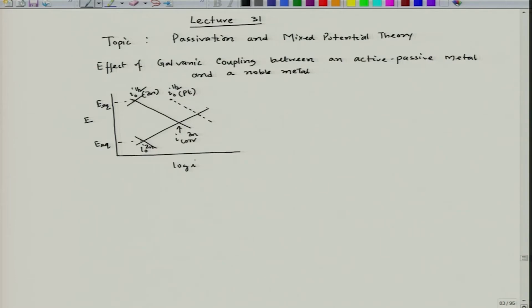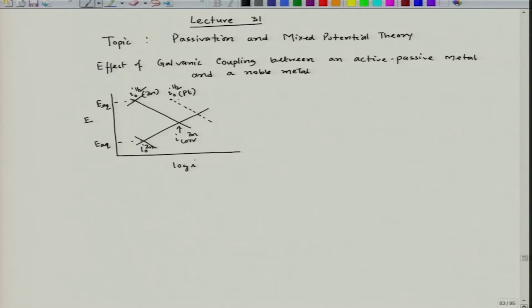polarization, cathodic polarization, but you have to add all the cathodic current densities and see a mixed potential point where your total rate of cathodic reaction is equal to total rate of anodic reaction. So, that is what we add: that particular hydrogen evolution reaction on zinc surface goes like this parallel line, because it is in a log scale. So, now this point becomes my I corrosion zinc when it is galvanically connected to platinum of equal area. So, that is why the corrosion rate increases.